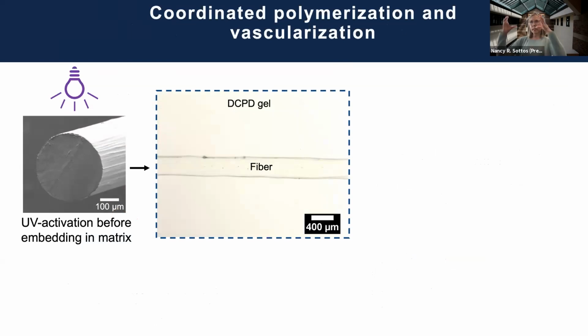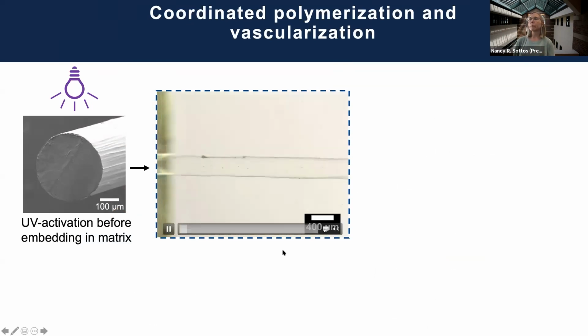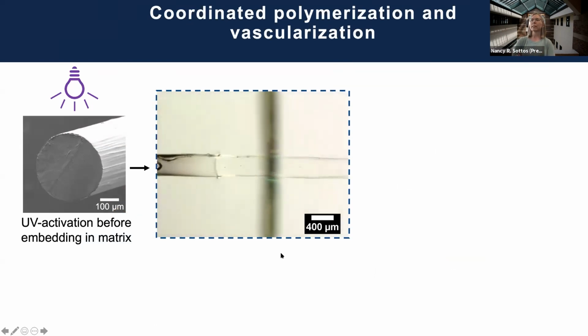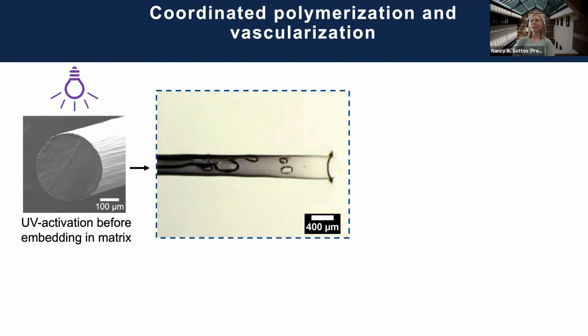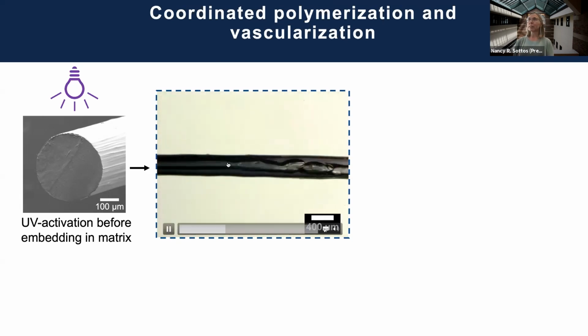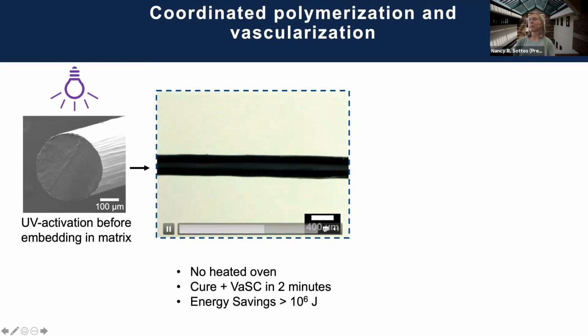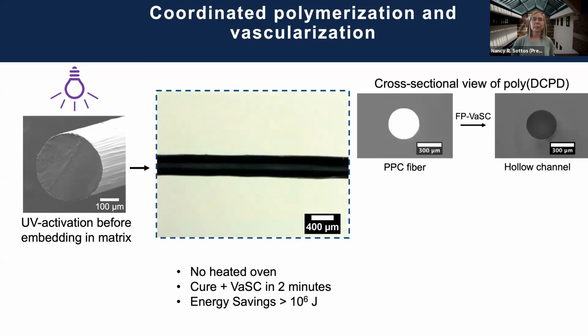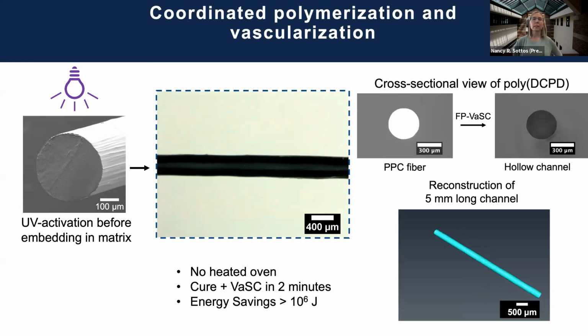We've got the fiber. This fiber is actually quite round with good fidelity, but as we look down on it, it's embedded in DCPD monomer. It's going to be triggered from left to right. And what you'll see is the polymerization front and the depolymerization front moving right here. So there's the polymerization front, and there's the depolymerization front lagging behind, as the material on the outside is going from monomer to polymer, and the material on the inside is going from polymer to monomer and evacuating, so that we get nice open channels in our DCPD. We can look at them under micro CT. They actually really have nice fidelity.